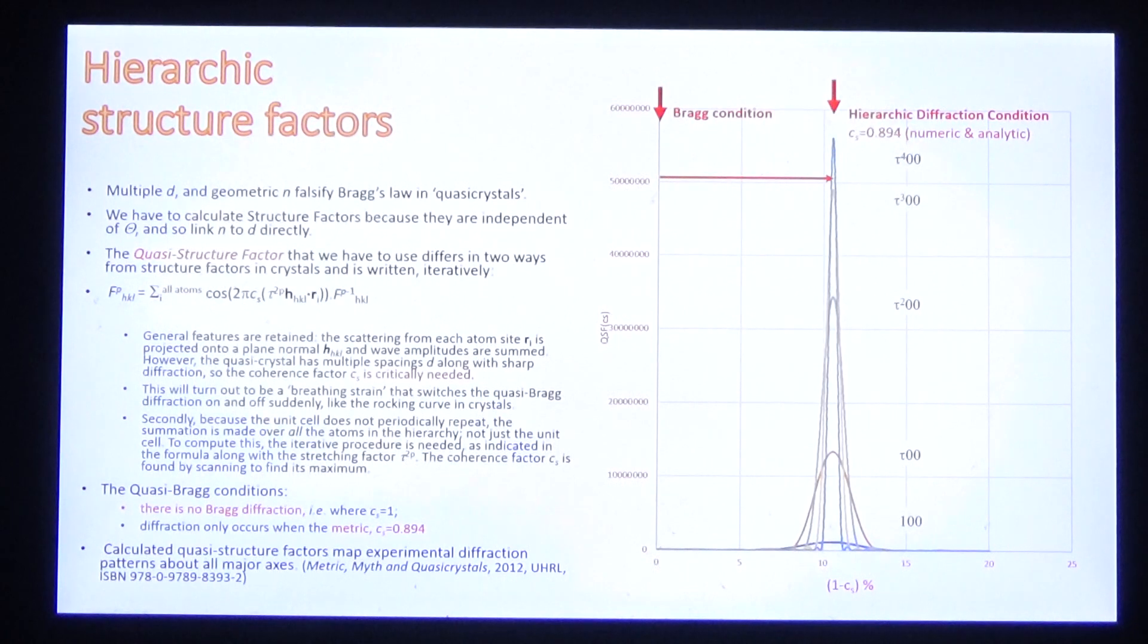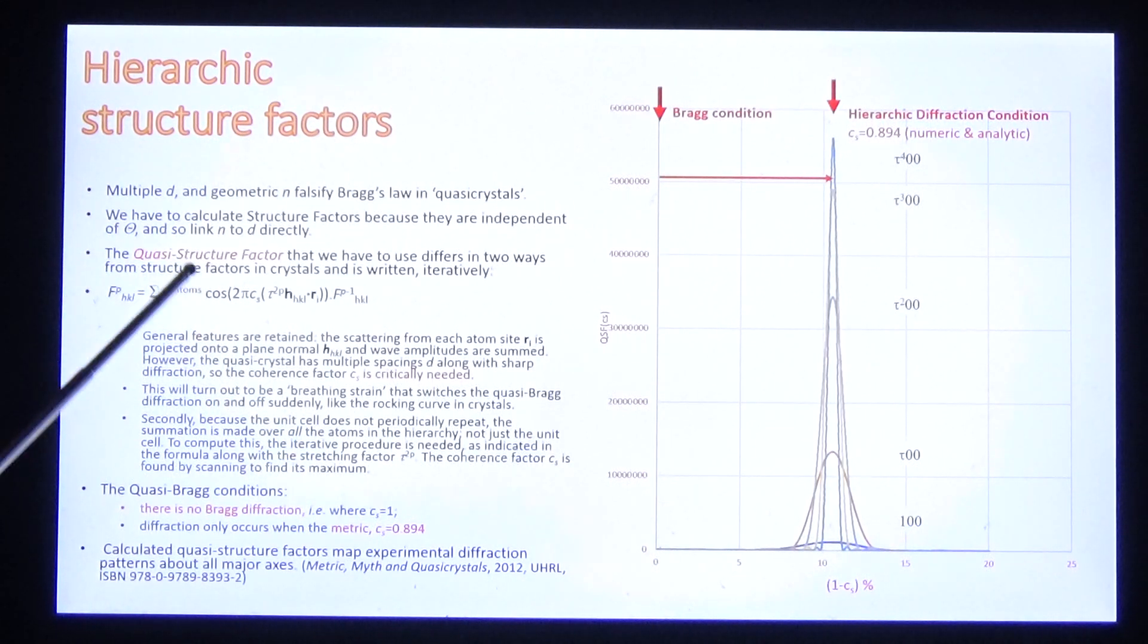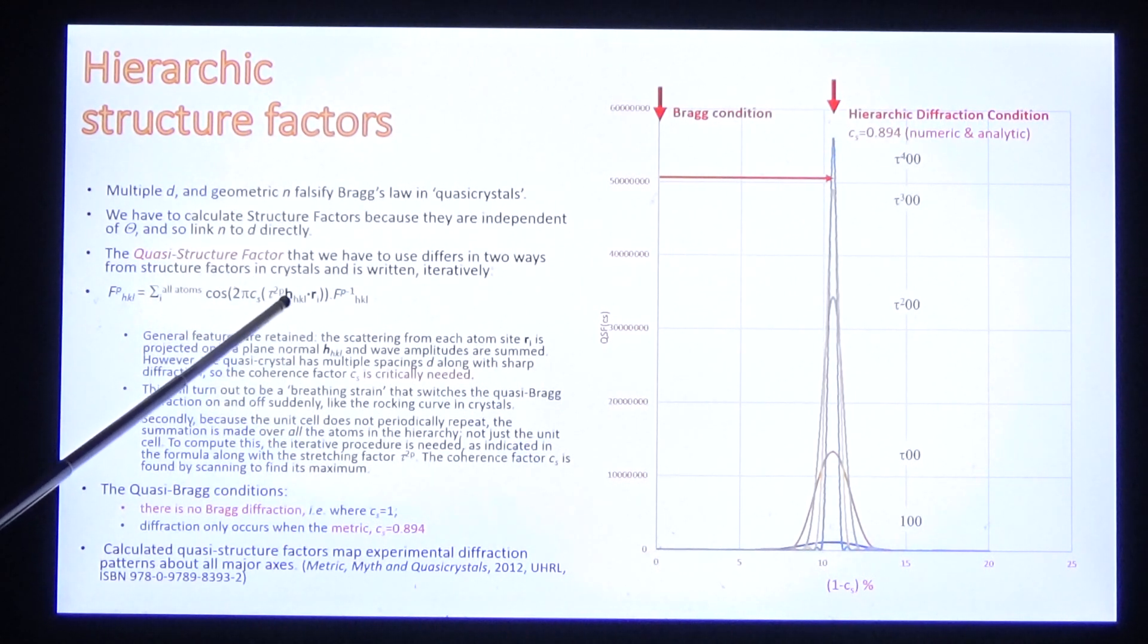Well, we can't use Bragg diffraction. But we can use the structure factor method. In structure factors, in crystals, the locations of individual atoms in the unit cell are projected onto a selected plane normal and the phasors added to produce an amplitude for a selected Bragg beam.